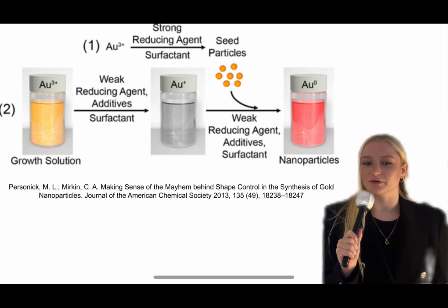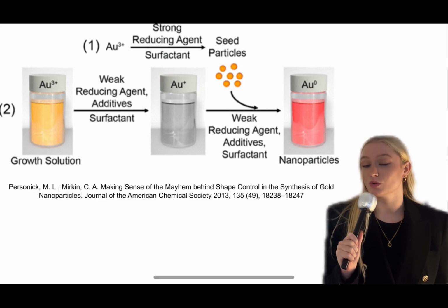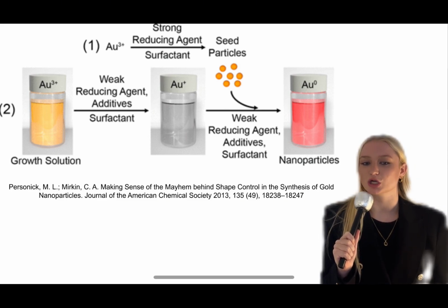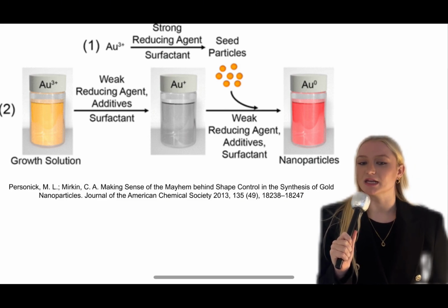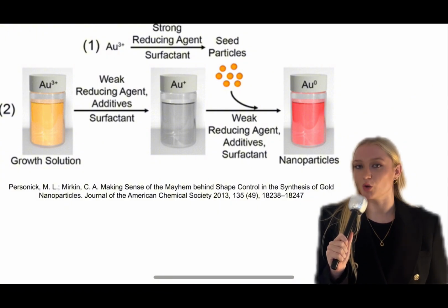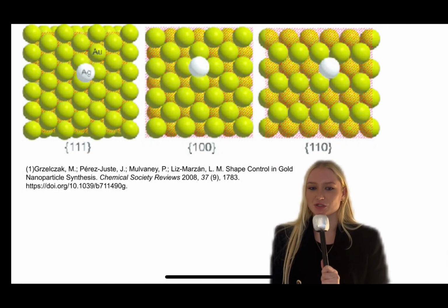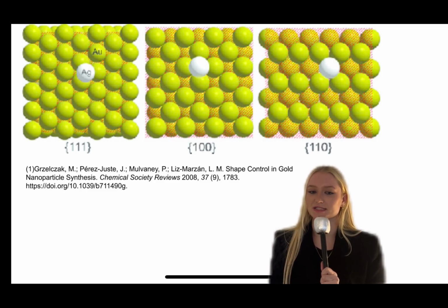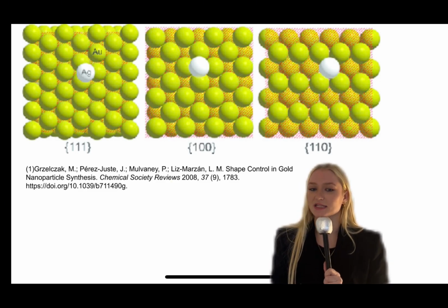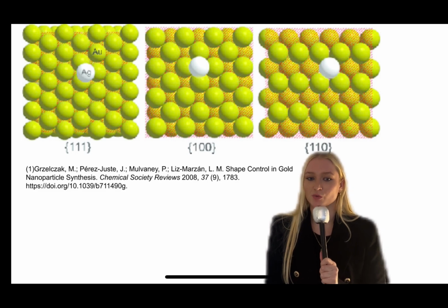The seeds consist of a metal center and serve as a nucleation site or origin of the crystal nanoparticle structure in a bottom-up approach, meaning that the nanoparticles are atomically assembled and grow over time. A key topic is silver underpotential deposition, a phenomenon in which a metal ion is deposited on an existing metal surface at a potential that is more favorable than the potential required for bulk deposition, resulting in the formation